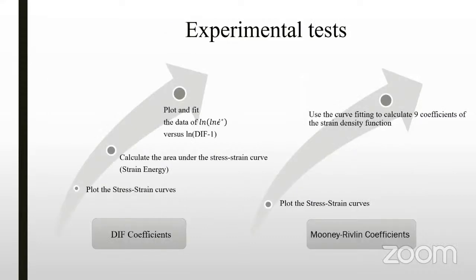These are the procedures I followed to calculate the coefficients. To calculate the dynamic increase factor coefficients, A and B, at first we need to plot the stress-strain curves, then calculate the area under the curve, which is equal to the strain energy, and then plot and fit the data of ln epsilon dot star versus ln of the dynamic increase factor minus 1. Then we can calculate A and B, the coefficients of the dynamic increase factor.